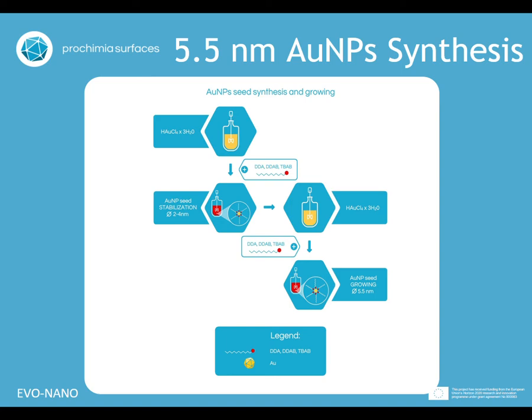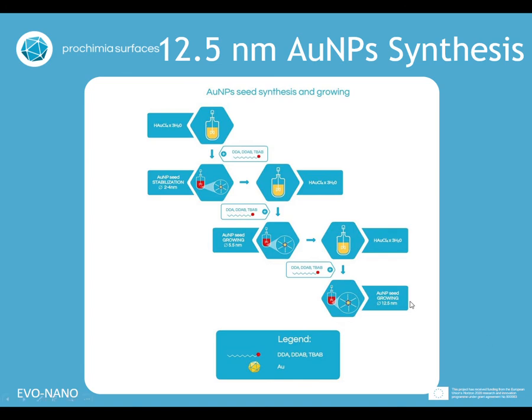Also, these 5.5 nanometer gold nanoparticles can be used further as growing seeds for the preparation of 12.5 nanometers. So as you can see, we can get about 2.5 nanometer, 5.5 nanometer, and 12.5 nanometer gold nanoparticles in the stepwise synthesis of these gold nanoparticles.